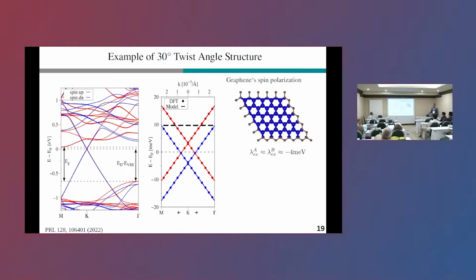If you place your Fermi level to this dashed line and you calculate the spin polarization that is on graphene, you will find it to be very uniform and negative. And the corresponding model parameters are the same for both sublattices and also negative. Now, where does this come from?